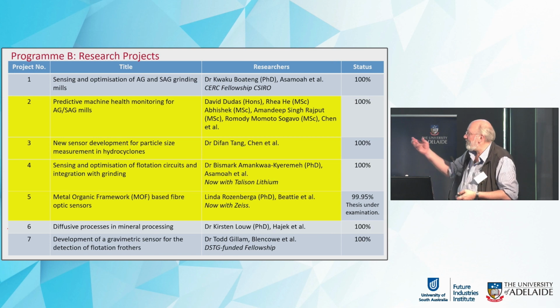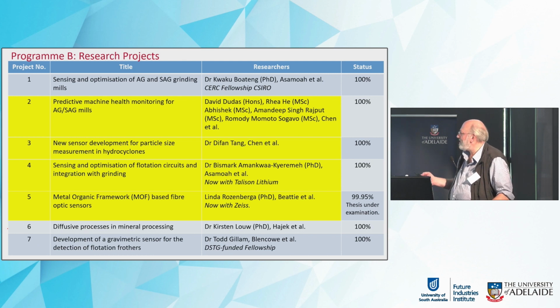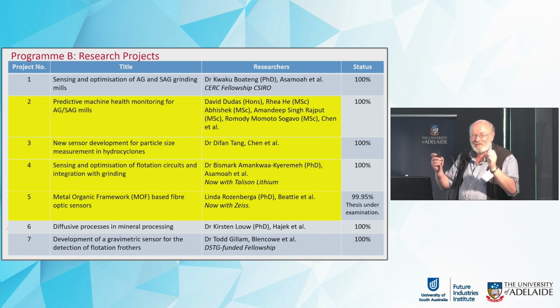So the idea behind this is you get metals absorbing to or in, it turns out to be to, these MOFs, which then change their spectroscopic characteristics, and you see a characteristic loss in peaks in the infrared when you have iron 2 absorbing to that. So it's a really interesting way of indirectly measuring the iron 2 concentration, and you whack it on an optical sensor. So those two projects, 5 and 6, work pretty closely together, and it's a real example of how the mathematical and the experimental can work really nicely together.